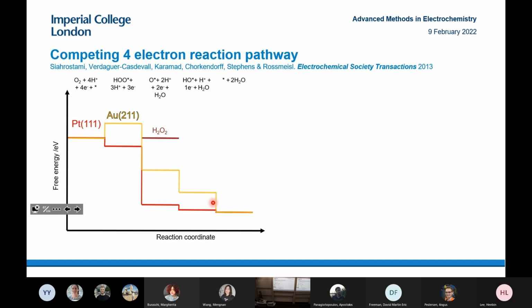Gold 211, which the theorists modeled as the active site for hydrogen peroxide production on gold. They see that, as I showed previously, it's uphill to form OOH, and it's still more downhill in free energy to form water, so you go via the oxygen intermediate, than hydrogen peroxide, but it's less downhill. So this could explain why there's less driving force to make water than there is on platinum 111.